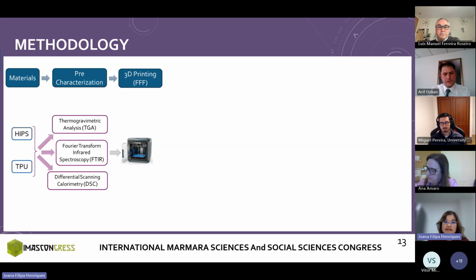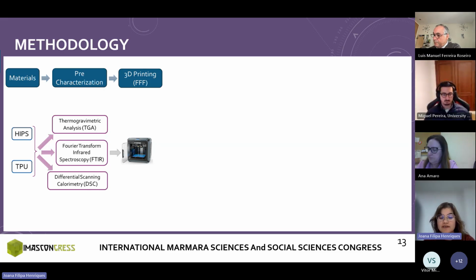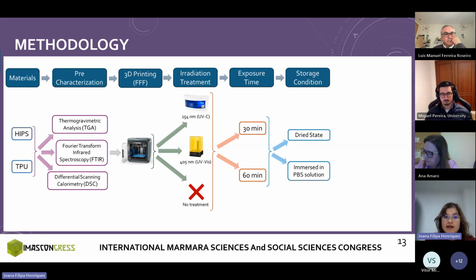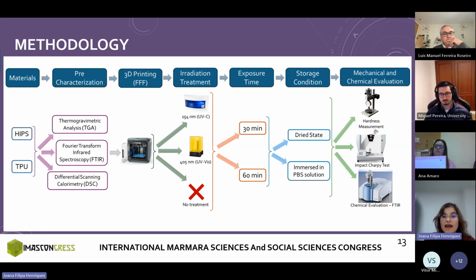Initially, we selected two different filaments that were chemically analyzed and thermally characterized to select optimal printing parameters. Then, the specimens were exposed to UV light for 30 or 60 minutes and stored in empty Falcons or immersed in PBS solution for 1 week. And finally, the mechanical properties were evaluated with Charpy test and hardness measurements,